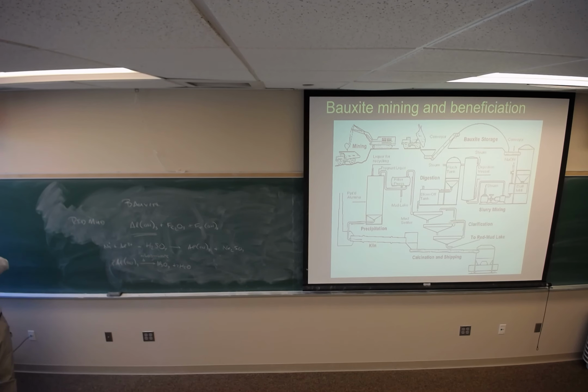A friend of mine figured out that the issue is that when you heat treat this material, because your temperatures are high, if you're above about 900 degrees C, the sodium goes into the vapor phase. Good? Okay. So when that material comes out of the calciner, if you vent that gas off of the top, the sodium goes with it. If you don't vent the gas and the material just cools, the sodium recondenses back on the surface of the alumina. Then you have to wash the alumina to remove the sodium, so you have an extra process step. He invented a process by which you vent that high temperature gas, and with it goes the sodium, and you can produce extremely low sodium aluminum oxide through the Bayer process.